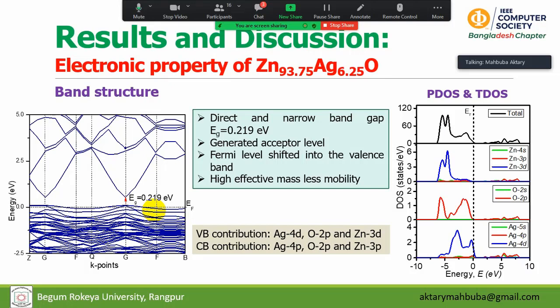And high effective mass is shown by the less curvature of this energy band diagram, and it has less mobility. And on the figure of right side, we can see the partial dose and total dose representation, and the valence band contribution was arised from the contribution or overlapping of silver 4d orbital, oxygen 2p, and zinc 3d orbital. And conduction band peaks arise from silver 4p, oxygen 2p, and zinc 3p orbital.